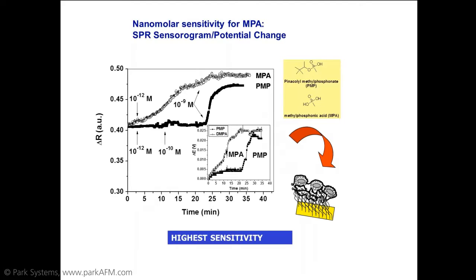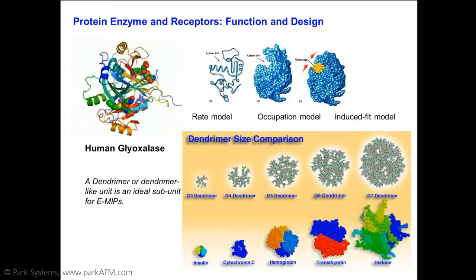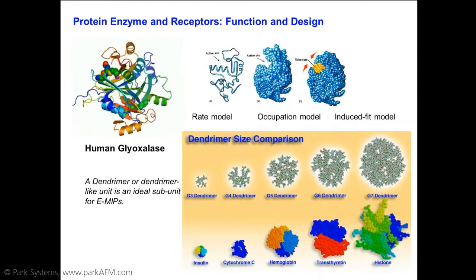In fact, the breakdown product of PMP is actually methylphosphonic acid. When we try to detect the breakdown product of PMP, we were able to reach up to picomolar level, or 10 to the -12. So the highest sensitivity can actually be observed with this system. Now, mind you, all these interesting results, we are working with a non-molecularly imprinted material. In other words, what if the system was actually designed to have a molecularly imprinted system from the ground up, and what would be the comparable performance? So let me describe the possibilities here.